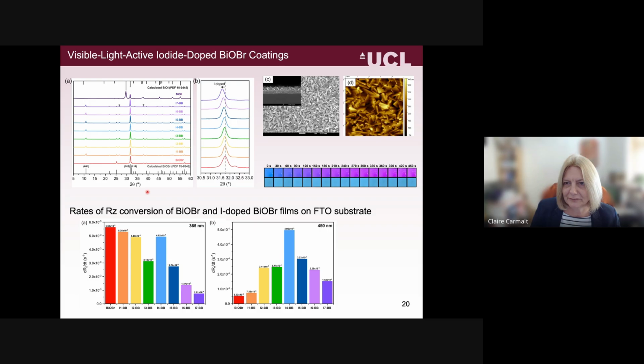And what we found, when we did the same photocatalysis under visible light, is we see the lowest activity from the bismuth oxybromide. That increases until the best one is the one with 2.7% iodine doped into the bismuth oxybromide. And basically what we're seeing is an uplift of the valence band edge. It's narrowing the band gap of your bismuth oxybromide, and that's the best size to get the most active photocatalyst.